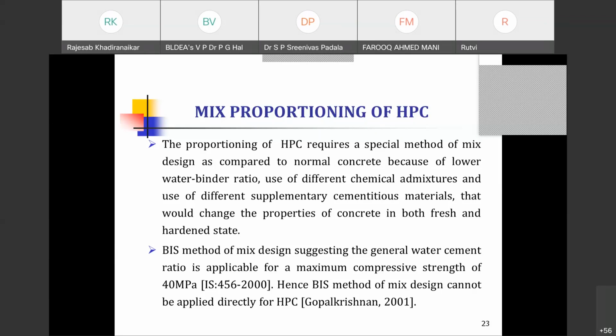So that is why the cement that you are choosing should be appropriately chosen. For high performance concrete, as you are aware, we must have a lower C3A content, and increased fineness is better. And it must be compatible with your high performance concrete, because compatibility issues will be there. Better you go for the fourth generation superplasticizers or HRWRs. It is C3A content that controls the rheological properties of your mix. So that is why we have to be cautious about C3A content. Around 5 percent C3A content is much better. Like this, cement is equally important, and coarse aggregates, their size, their content, everything is important.